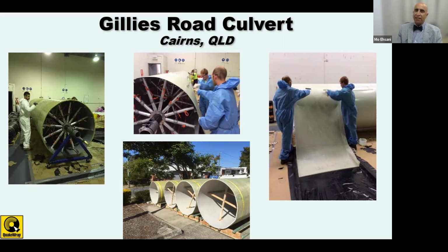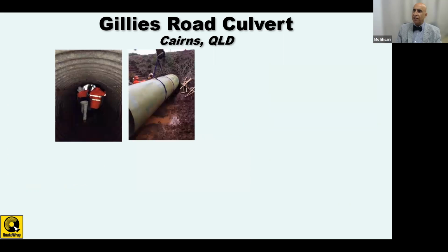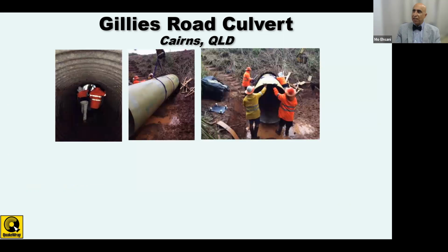For this particular job that I'm showing you, we were repairing 80 feet of culvert in Australia. So we made 4 pieces of that pipe, 20 feet long each, as you see here, and then they were shipped to the job site. This is the deteriorated culvert, and it was deformed. So we custom made the pipe to fit the lowest diameter at the lowest point of the culvert. Then the pieces were pushed into the old culvert, and the edges are connected together with that wet layup system in the field. We can apply the fabric because this is large enough for man entry.